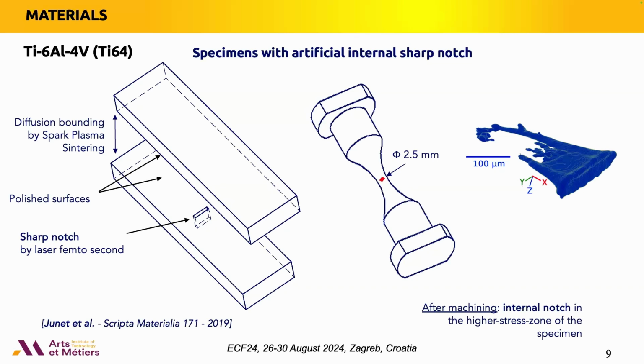And then we polish very precisely the surface of 2 plates, and then we bond the 2 plates by spark plasma sintering. This process is made under vacuum, so it is interesting because in this case, you finally obtain a piece of titanium with a very sharp notch in vacuum in the center of your specimen. And then after assembling these 2 plates, the specimen is machined by turning. Of course, we have obtained precisely the position of the sharp notch by X-ray tomography before the machining, and then we are able to know that the defect is in the center of the specimen. You have here a 3D image of the defect. Its typical dimension is a length of around 200 micrometers, a width of 120, and an opening of 20 micrometers maximum, typically 15, sometimes 20.